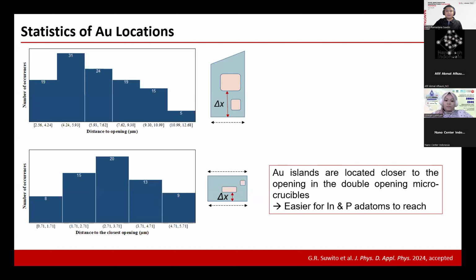When we try to draw a distribution of the main gold islands, so main islands are the bigger islands inside the crucible, it looks like this. This distance to the opening, indicated as delta X, is the distance between the opening, the double arrow in here, and the largest gold island. So I took the largest one.